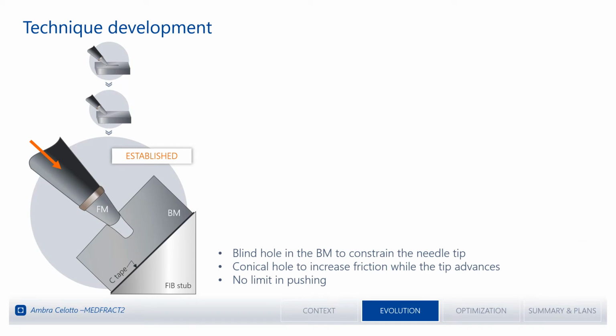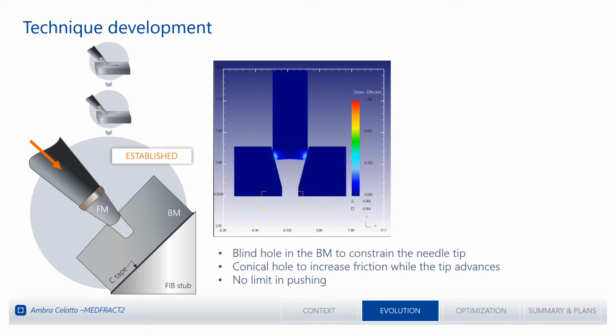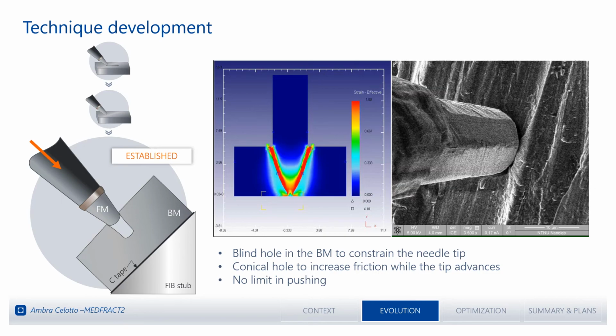For doing so, we designed a new setup that actually turned out to be the established technique at the end. And this is made by tilting the base metal 45 degrees, so making it perpendicular to the feeding direction, so to the hybrid needle axis, and by drilling a blind hole in the base metal. As in these simulations here, the filler metal is meant to fill the hole and to create bonding at the interface between the two metals, of course. And because of redeposition when drilling the hole in the base metal, the hole is expected to be conical. And this is actually a favorable condition for us because this increases the friction forces while the needle tip is advancing inside the hole.